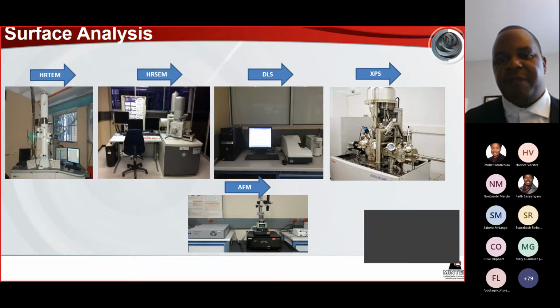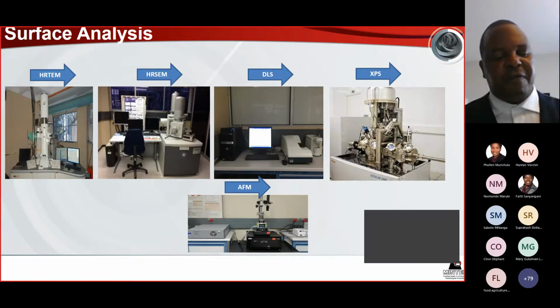depending on the orientation of the particles, you may not get all the information. So what it means is if you have something that looks somewhat like a rod and you're trying to measure out the size, depending on how the light comes through, if it comes through from the elongated side, you might have the particle size that looks much larger than it should otherwise be. On the other side, it may also depend on the behavior of the material in a medium. So some materials, when you put them in a medium, they swell up. So the size that you measure out using this could be something else, and it could be far from the reality. So those are some of the things that one has to be aware of as you make use of this.